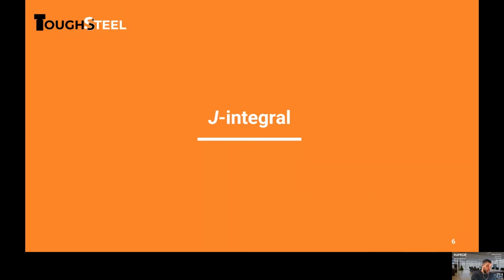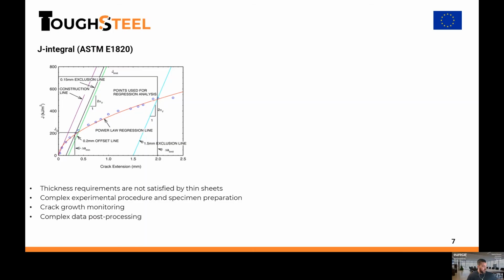First, let's see the J integral. Let's talk a little bit about this J integral procedure. Maybe it's the most well-known and well-established procedure to evaluate the fracture toughness of ductile metals. You can measure the J integral following the procedure described in ASTM E1820. This standard describes two procedures: a basic procedure to evaluate a single initiation toughness value, J1C, or a resistance curve procedure to evaluate the J resistance curve, like you can see in the image, where the J values are plotted as a function of the crack extension.